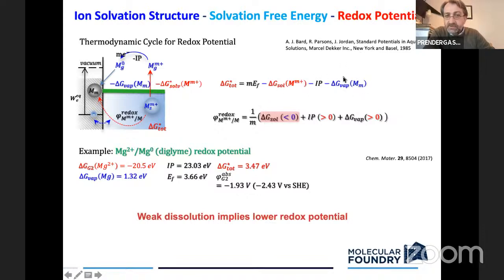And so if those are constants and you can change the properties of the electrolyte, change the solvent, change the concentration, and so on, then the redox potential is really dependent on the solvation environment to a certain degree. You don't often see it stated that way. When you look up tables of redox potentials for different species, they're almost always in water. And the standard assumption is that that is the redox potential of that species, but actually it should be a function of which solvent you used. That's the first thing to keep in mind. And then what this implies is that if you have weakly dissolved species, they will have lower redox potential. It will be easier to reduce them.